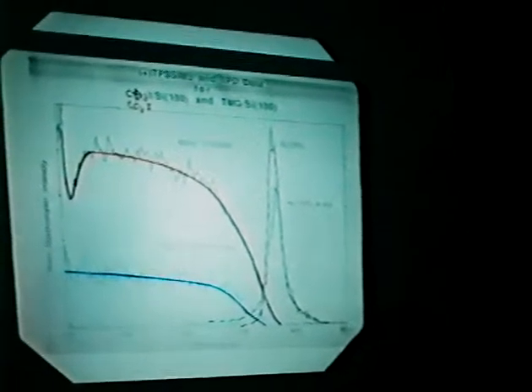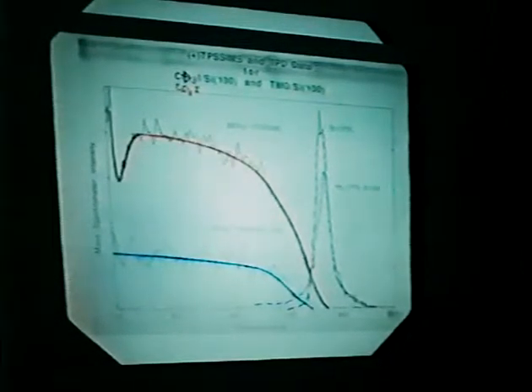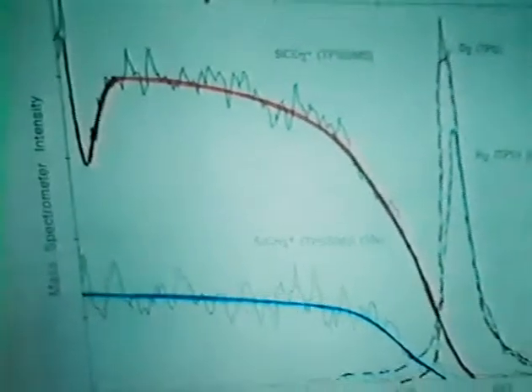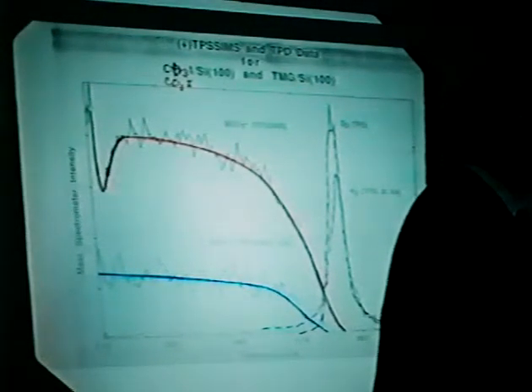Here's a temperature program version of that particular problem. What you see here is TPD, temperature programmed desorption, and static SIMS in a temperature program mode superimposed. In temperature programmed desorption, the only molecules we see desorbing are hydrogen, just below 863 Kelvin on this particular scale, and the parent molecule, which is desorbing way down here around 115 Kelvin. There's a little disagreement between this work and some of the very nice work that Rich Maisels has done about the presence of methane. We've not been able to find methane desorbing under our conditions.